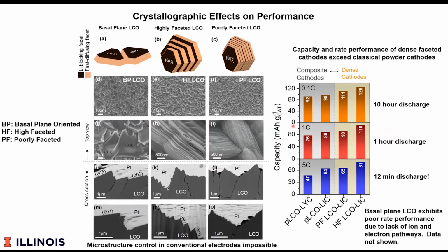As I mentioned, there are very strong crystallographic effects. If you have it oriented so that the 003 planes are facing up toward the solid electrolyte, the performance is rather poor. I don't even show the data here on the right because the capacity is too low. On the left are two different kinds of faceting depending on how we grow it. The highly faceted material, which exposes a considerable number of the 101, 104, and 110 planes, has the best performance. Even the poorly faceted, which is really just this but with a much higher step density, still has good, but not as good, performance. And if we look at the capacity here, this is the total cathode capacity, the composite cathodes versus the dense cathodes.